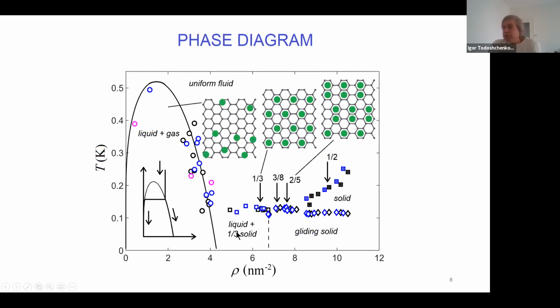Then we have this stiff 1/3 solid here, and there is a quantum phase transition to the so-called gliding solid. At higher temperatures, this gliding solid turns to normal, which then melts to the fluid. Here I illustrate the 1/3 solid. 1/3 means that every third carbon hexagon is occupied with helium. And this gliding solid we attribute to the dimer solid, which consists of bosonic dimers